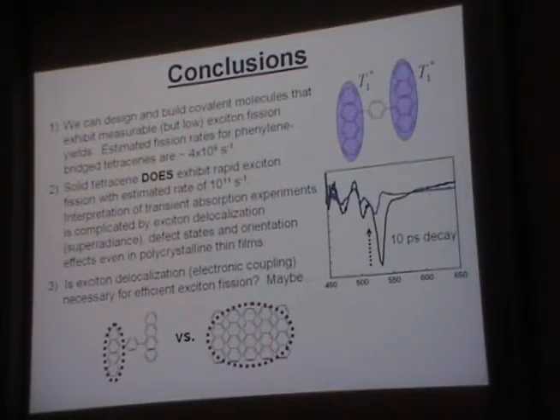It may be that this is a symptom of a condition, namely a low-lying charge transfer exciton state that enhances both processes. It increases your electronic coupling and it increases your fission rate. And if that's true, it's bad news for molecules like this, because it's not clear how you create a charge transfer state. Here it's easy because you have this huge polarizable medium that can lower all those energies. Here it's not so easy to see how you would get a charge transfer state to be close in energy easily.